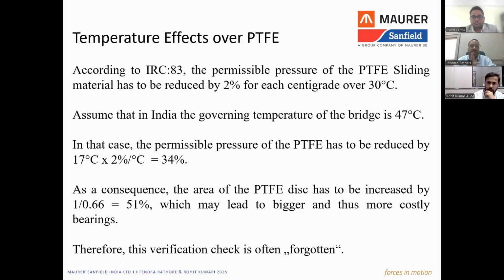The second thing: all codes, whether it is Eurocode or IRC 83, say that for an increase in temperature beyond 30 degrees centigrade, you have to apply a 2% reduction in the permissible pressure on this material. Like here we have compiled a calculation.